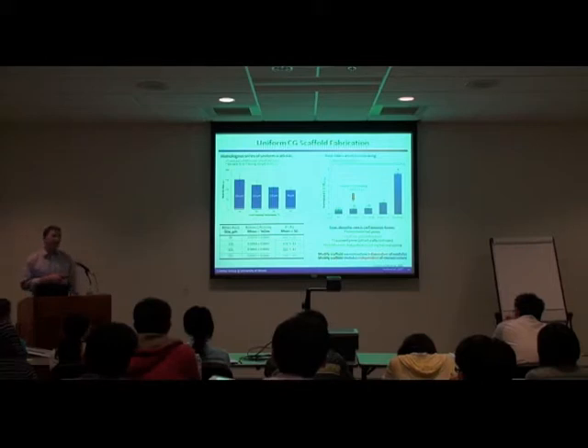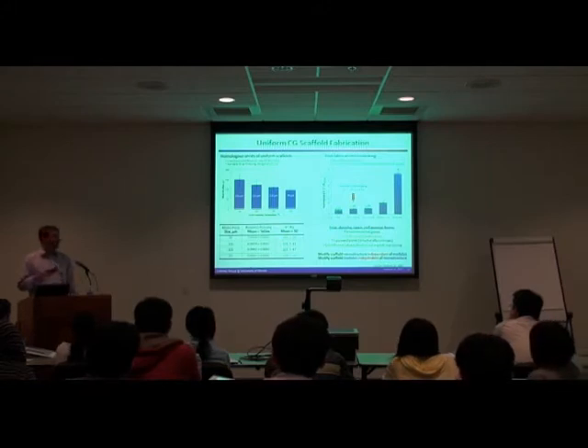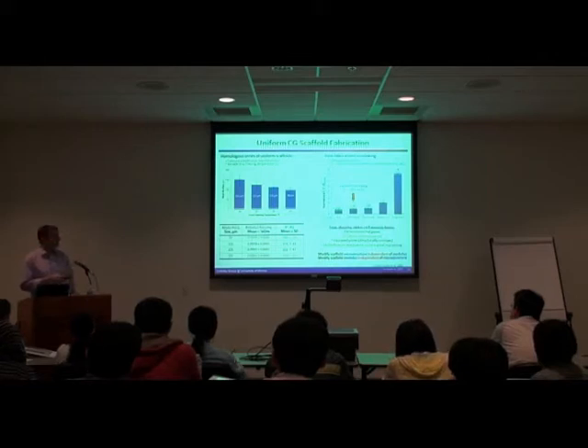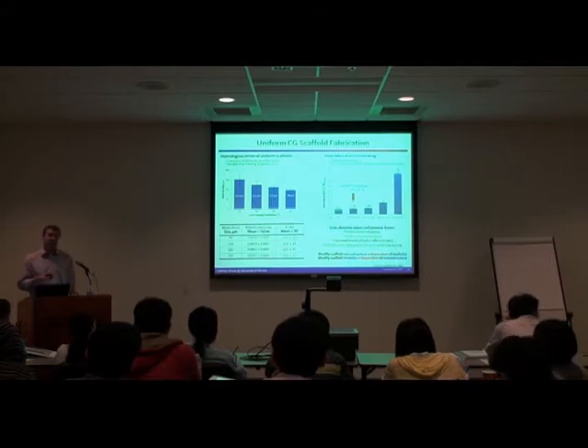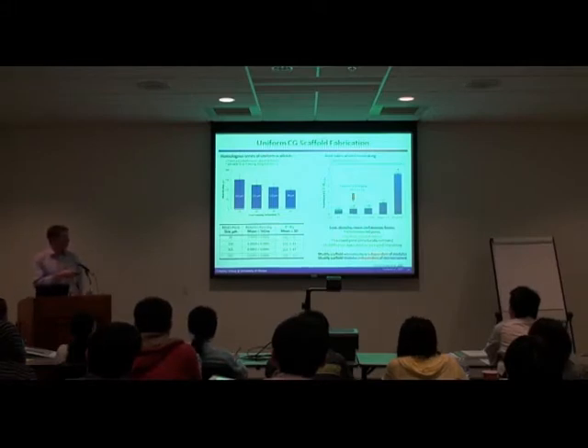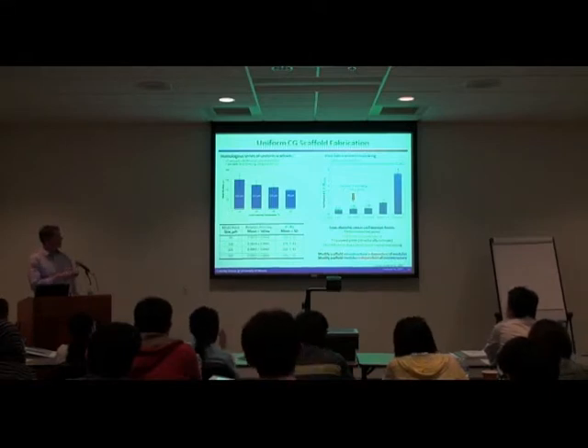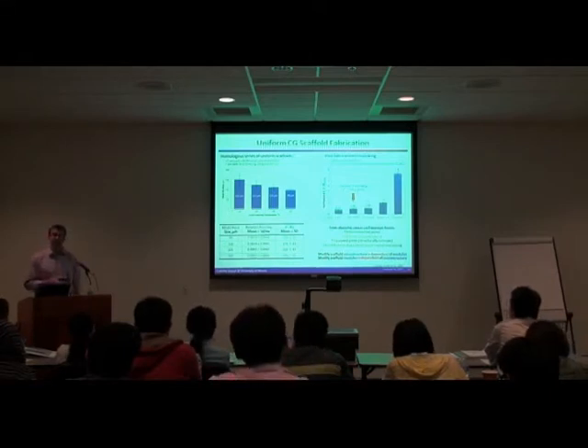And one would think, well, how do the mechanical properties of these materials change? The cellular solids modeling suggests that the modulus of this material depends only on the relative density, not on the pore size. And that's in fact what we find. So we can change the pore size of the scaffold and keep a constant modulus because we've kept the relative density constant, or we can keep a single biomaterial and change the cross-linking density to change the mechanical properties. So this allows us to go back and forth between changing microstructural features and mechanical features independently of one another. And that's sort of the basis for a lot of the work we started to do.